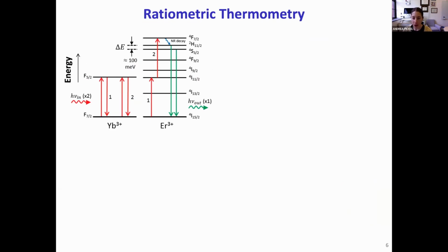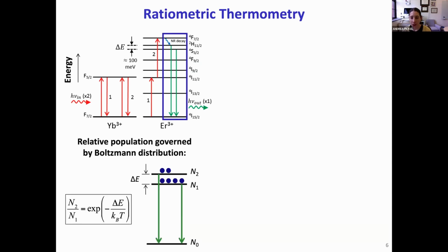But the main reason that we're interested in these UCNPs is that they have some particular temperature-dependent emission features that are appealing for thermometry. So as I said a moment ago, the upconversion process begins when the ytterbium absorbs two near-infrared photons and transfers this energy to an erbium ion. Next, the erbium decays non-radiatively to a lower energy excited state before returning to the ground state by emitting a green photon. This is clearly a complicated system with many different energy levels and transitions, but we can really understand the essential temperature-dependent physics by looking at a simple three-level diagram for erbium.